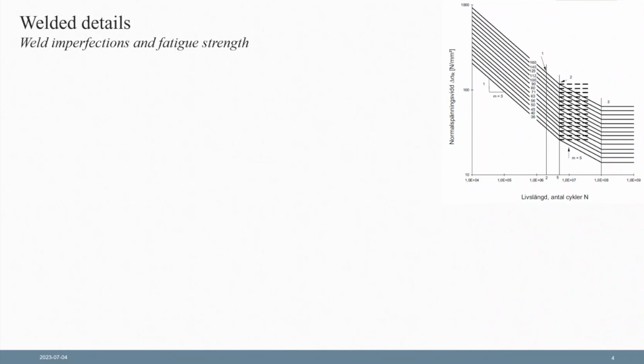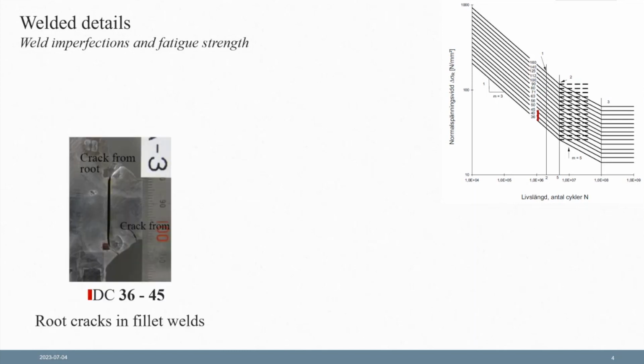These are commonly parallel slope SN curves. The curves that you see now are those in the present version of Eurocode. And we have curves from the highest, which is 160 megapascal at 2 million cycles, that describes the base metal, to the lowest SN curve, which is 36. And these curves cover all kinds of welded details that we can find in bridges, or at least they are meant to do that.